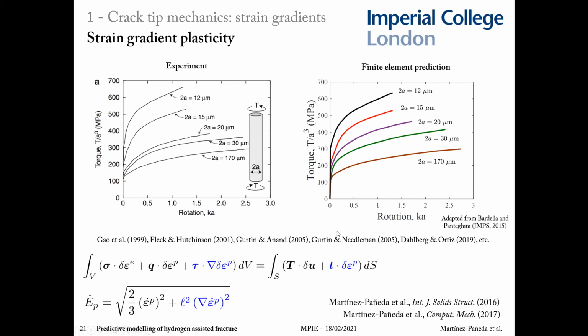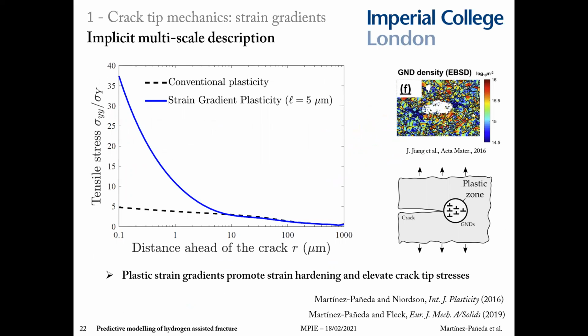And one can quantitatively capture those dislocation hardening mechanisms that you see when you have large gradients of plastic strain confined into a small volume. You can see it here, the finite element analysis of the torsion wires that I showed you before. And my contributions here have been on 2 fronts, mostly. One, in the development of robust computational schemes, as these strain gradient plasticity theories are typically higher order, involving higher order stresses conjugate to gradients of plastic strain. And consequently, there are some challenges associated with the numerical implementation. But also I've been working mostly in applying these strain gradient theories to gain insight into crack tip mechanics.